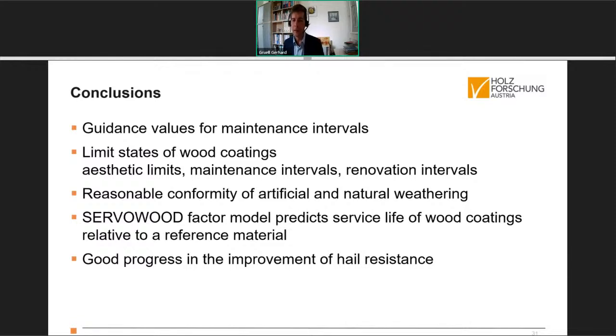We found reasonable conformity of artificial weathering and natural weathering according to the EN 927 standards, and we think a rough prognosis is possible from artificial weathering on the durability in natural weathering. At least you see a nice picture of the characteristics, how a coating system degrades during weathering. The SERVOWOOD factor model predicts service life for wood coatings relative to a reference material, and this reference material brings in long-term experience in the model, which is a very nice approach, and the factor model brings about the possibility to improve the model with consequent research on specific and additional factors later on. And we've seen good progress in the improvement of hail resistance in our research.